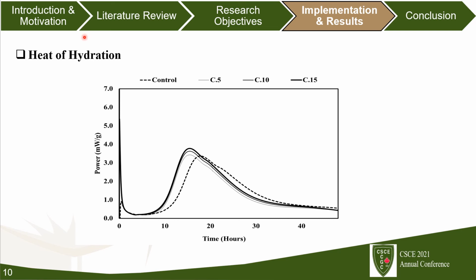After that, we examined the heat of hydration. Increasing the limestone content influences the hydration kinetics, as we can see here in this curve. Increasing the limestone content shifts the peak to the left and increases the hydration peak by 15% for the 15% replacement mixture compared to the control mix.